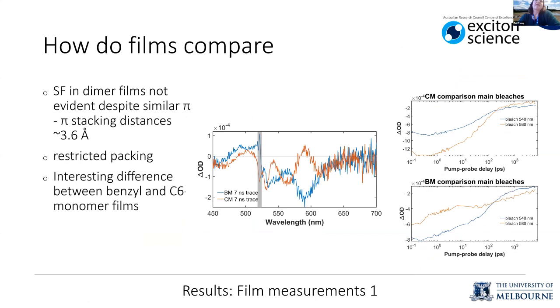And then the last thing to look at was how this compares to thin films. And the interesting results from the thin films are that if you make a thin film of dimers, it appears that the bridge in the dimer seems to disrupt the packing. So we didn't see any long-lived signals indicative of singlet fission in the dimer films, but we do see it in the monomers. And this was despite the stacking distances between the chromophores being roughly the same for basically all of the films that we made. So that was an interesting result, which I still need to look into.